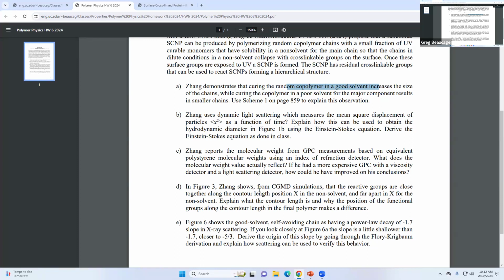because it's in a small fraction, the different moments of molecular weight are the same value if it's monodispersed. So if they aren't, then you know that it's got some other story to it, like it's this branched sphere thing or some other branched polymer or something else going on. But the light scattering will give you the actual molecular weight. Anyway, anything else? There's one other, anything else on the questions in this? Yeah.